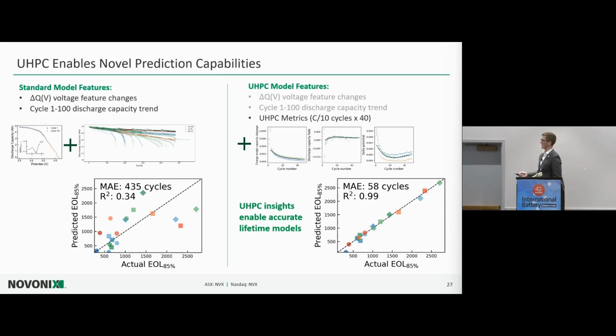However, if we just layer in these UHPC features of these slower cycles, C over 10 cycles, we have our coulombic efficiency, we have charge endpoint slippage, we have our delta V, we have our fade. And we layer some of these metrics in. All of a sudden, we take some of the kinetic information from the first 100 cycles, we layer it in with this electrochemical information about what's happening, and our models perform incredibly well.